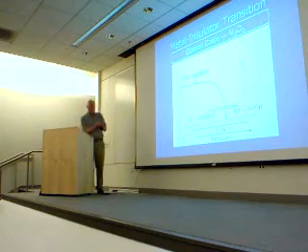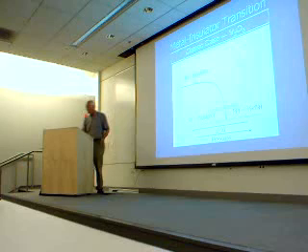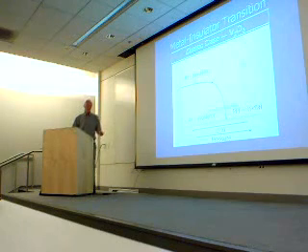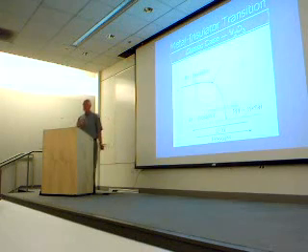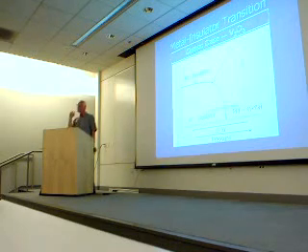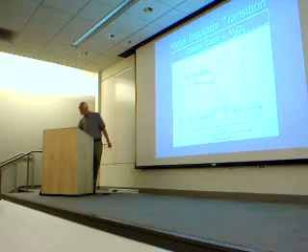And we know this is insulating in the sense that if you do an electronic spectrum, it still looks like it has a gap. All these features look like there's a gap. So there should be a transition between these two states, or it could be a gradual transition. And this is exactly what Mott was talking about. Would you have a gradual transition from a metal to an insulator, or should it be a first order transition? I think you can't just prove that just by thinking, but you can think of it as an interesting question. And in this system, it's a first order transition.